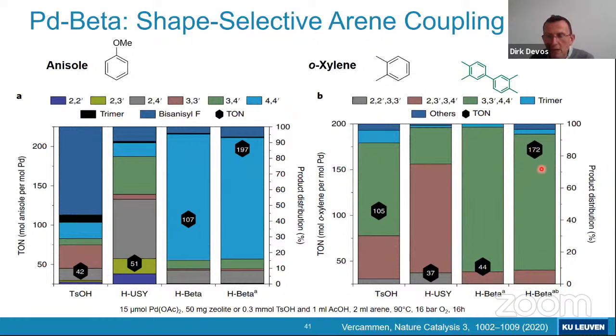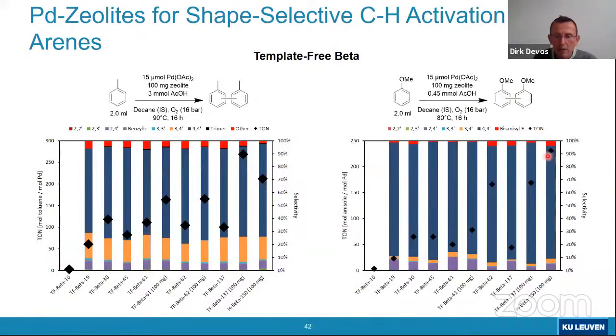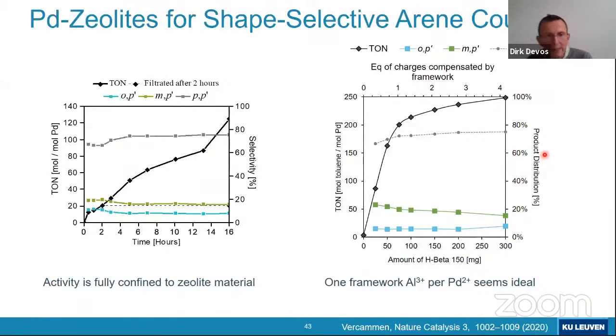Same story actually with the palladium beta and orthoxylene. That was a bit the starting point of all this, because that's a reaction that also works rather well, or very well, with the homogeneous catalyst. But you see that again, in comparison with, for instance, a Y-zeolite or the paratoluene sulfonic acid, even without any special ligand like the fluoropyridine, you get a very high positional selectivity for this desired 3',4' isomer of the orthoxylene, coupled with, again, high turnovers for this palladium beta catalyst.